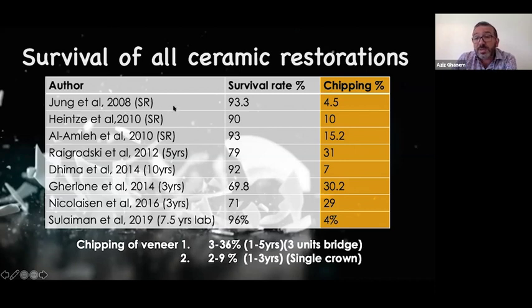And for some of them, the core was zirconia. Some of them, the core was alumina or lithium disilicate. What I want to highlight and make clear is that the delamination problem, or the chipping problem of the veneer, is the main reason for the failure of the all ceramic restorations. So, for example, right here, this is a study in 2012 looking at the 5-year survival rate of all ceramic restorations. As you can see, it's about 79% survival rate of the restorations, and 31% is the